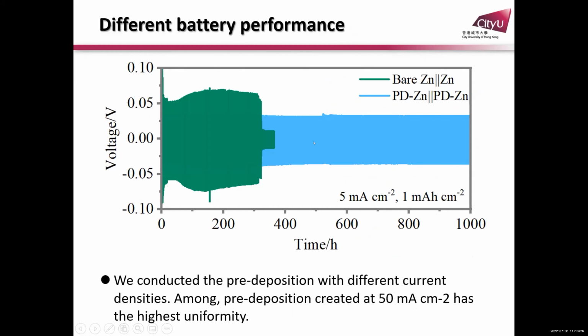Okay, so according to our observation, we propose that pre-deposition of zinc can also be a strategy to stabilize the zinc. That means you start from zinc before you use it to assemble full batteries. You use pre-deposition at a certain current density, which should be very large. Then the surface gets much more uniform.